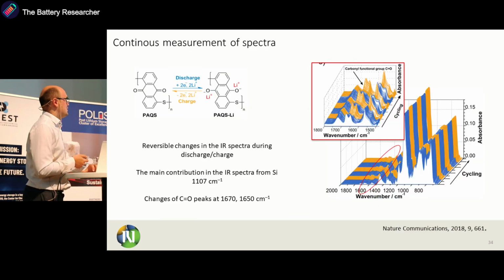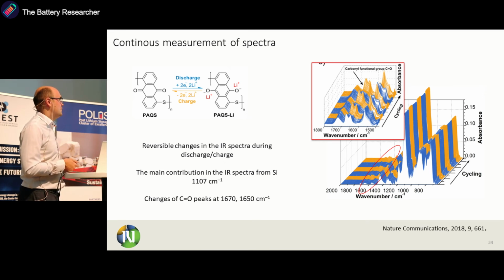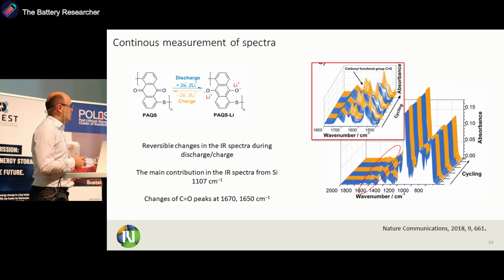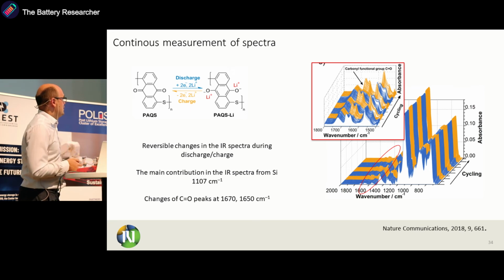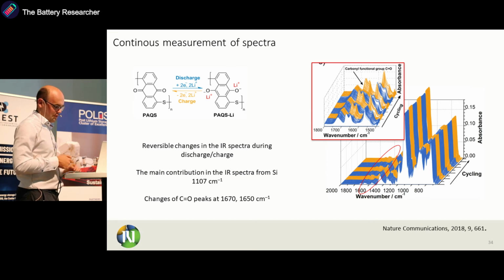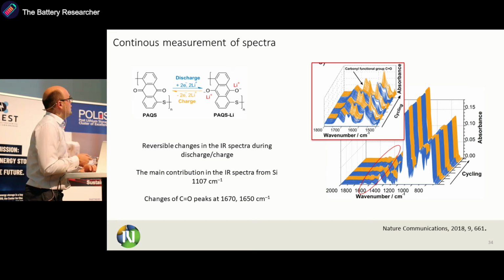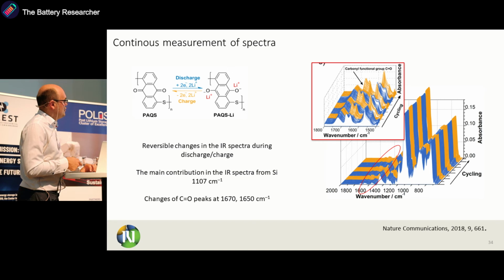This is quite nice, but the issue with the silicon wafer and the whole cell is the fact that you see also the stuff that you're not interested in. So basically the strongest signal that is here is the silicon wafer, and then you have contributions of the electrolyte and of your binder. But luckily for us, this carbonyl has these interesting peaks here. If we zoom in on this area, we can see quite nicely that this carbonyl peak decreases during discharge, and it goes up in charge, and so on again.